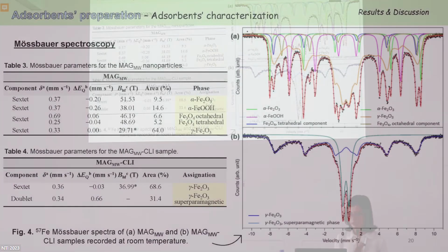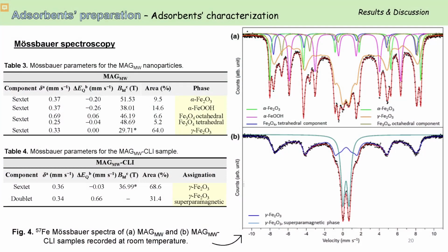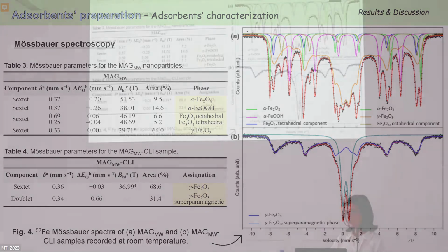To determine the iron oxide phases present in the pure magnetic particles and magnetic clinoptilolite, both obtained by the microwave-assisted method, Mössbauer spectroscopy was used. The results indicate that the dominant phase in both samples is maghemite. But as we can see on the first spectrum, the pure magnetic particles, in addition to maghemite, contain a handful of different iron oxide phases, while the formation of iron oxide on clinoptilolite results only in maghemite.